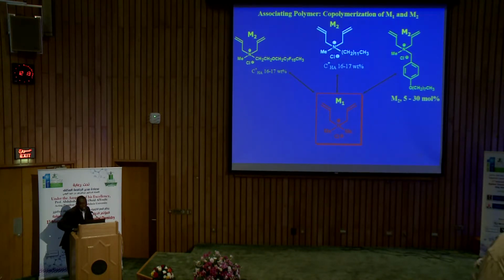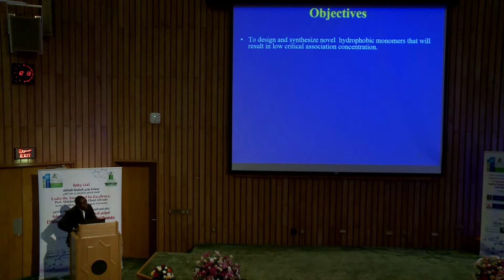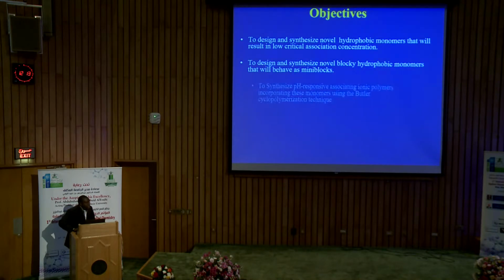Therefore, we try to synthesize a monomer that will look like a mini block so that we can achieve association at a very low concentration. So our objective is to design and synthesize a novel hydrophobic monomer that will result in a low critical association concentration. We also design a novel monomer that will have miniblock nature, which is called triple-tailed. And we also have a polymer that is pH responsive, that is, an ionic polymer, which we can make either a cation or an anion.